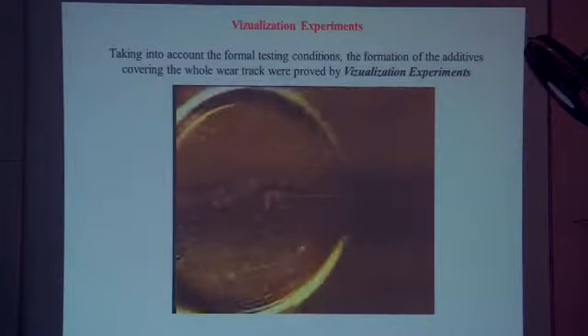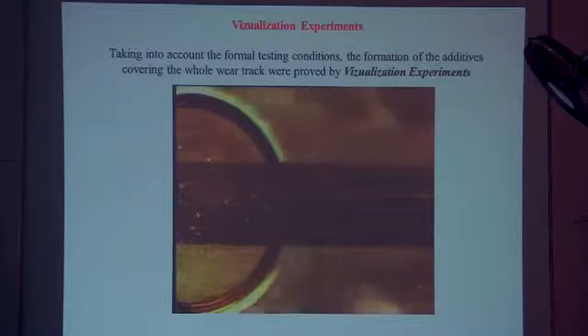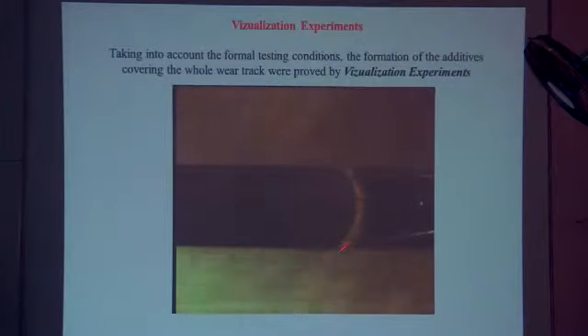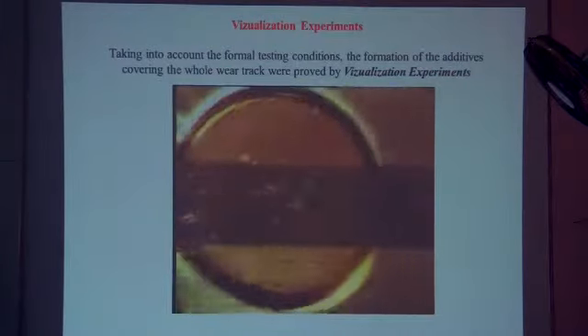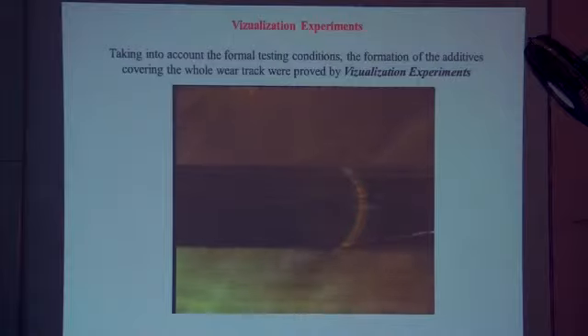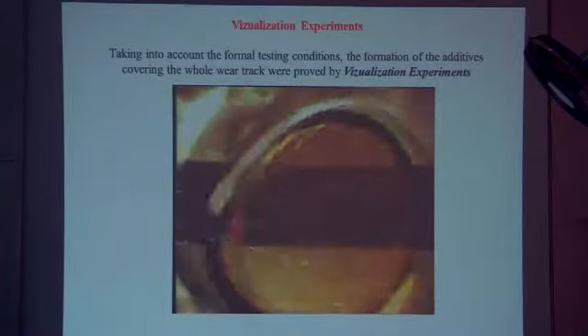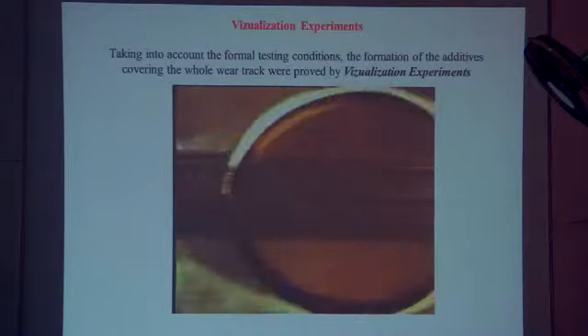The white patches are more visible. So at the end of the test, these patches are formed as additive layers on the surface. You see these patches are getting more, increasing on the surface. That's very interesting. Much more visible now. Yeah, you see it covered like this. Here is where they start to form.